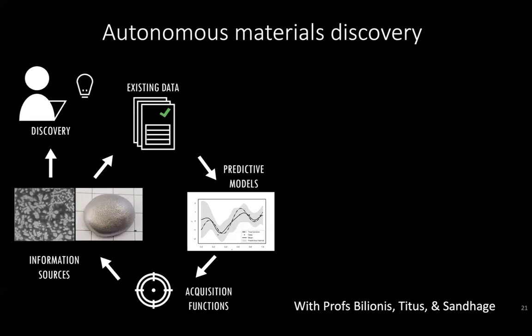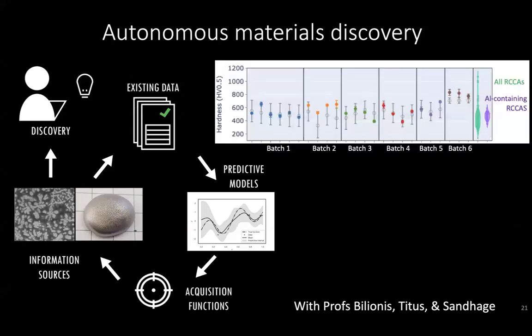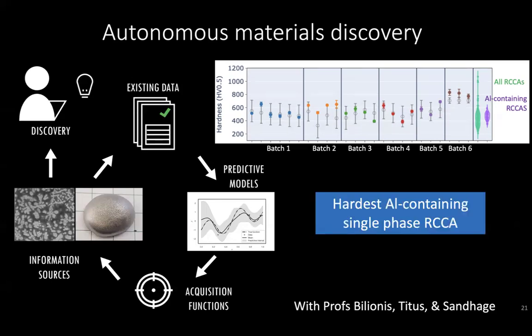We go to the lab. This is not autonomous, okay? It's an actual student that takes cues from the model and runs the experiments, okay? And so these are the results, batch per batch. And in about 6 batches, about 23 experiments or so, we found the hardest aluminum-containing high-entropy alloy, the hardest aluminum-containing complex concentrated alloy, in very few experiments.